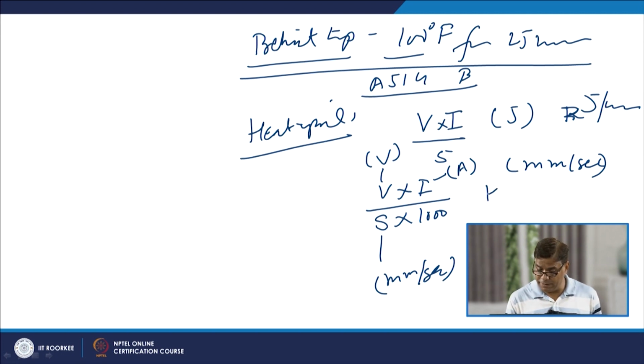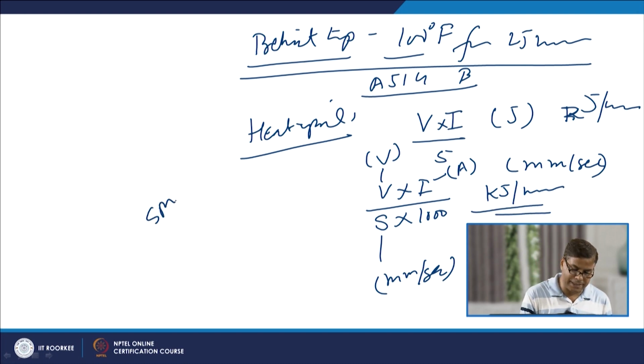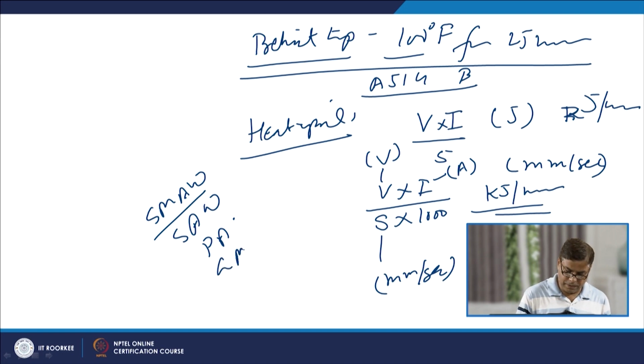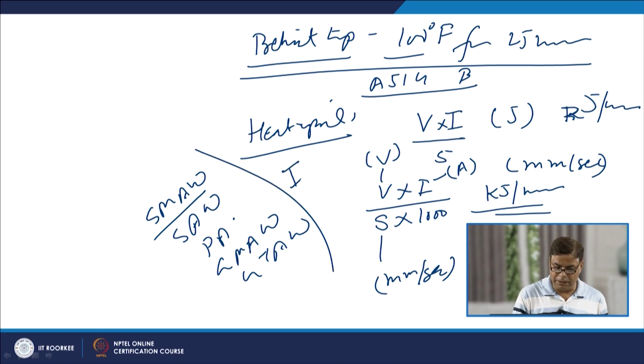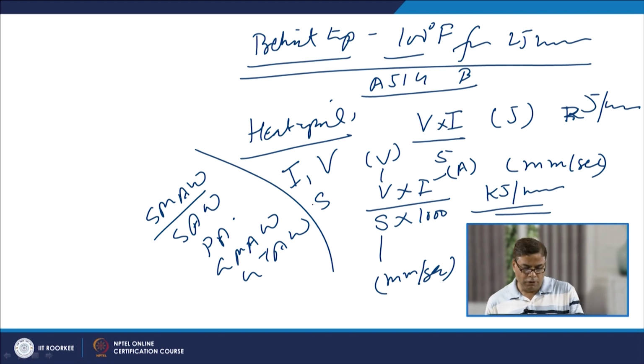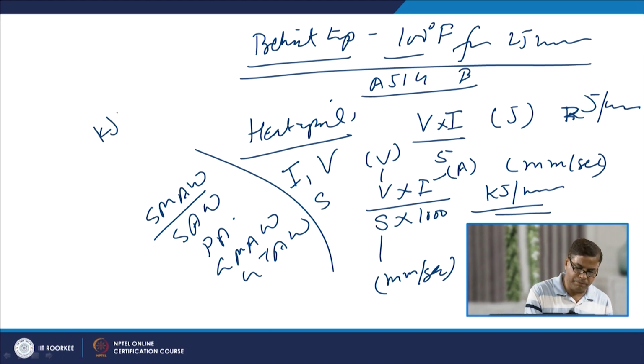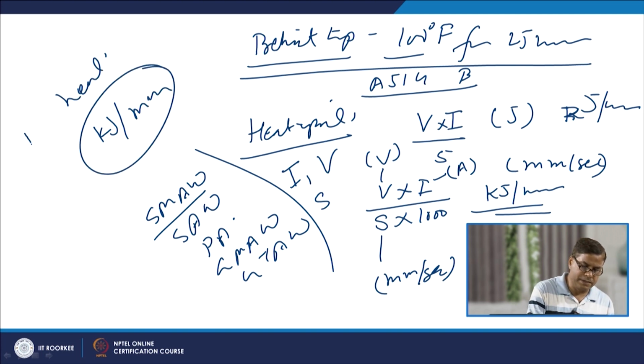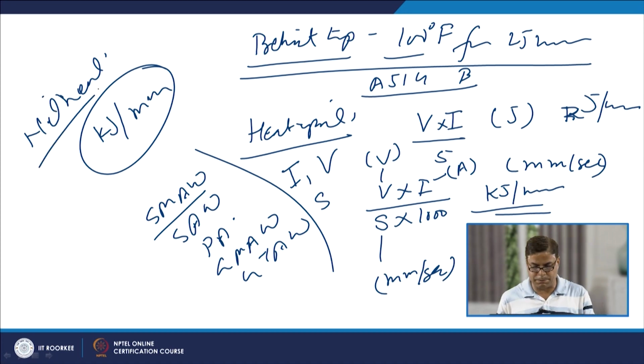This is what will be giving us kilojoule per mm. So, for a given welding process, whether it is SMAW or SAW or PAW, GMAW or GTAW, whatever the process is, we will be using particular value of the current and the voltage, and the arc will be travelling at a particular speed. So, for those various combinations, we need to see that our kilojoule per mm net heat input, this is called net heat input, does not cross the specified value.